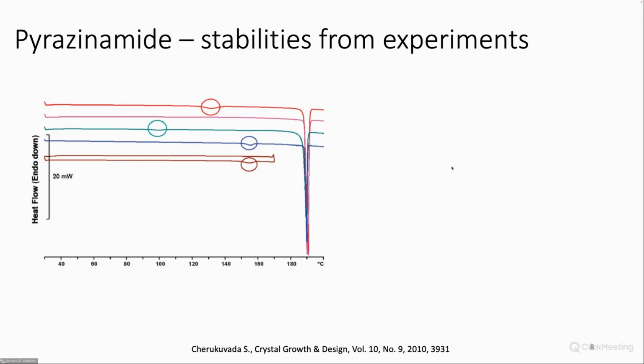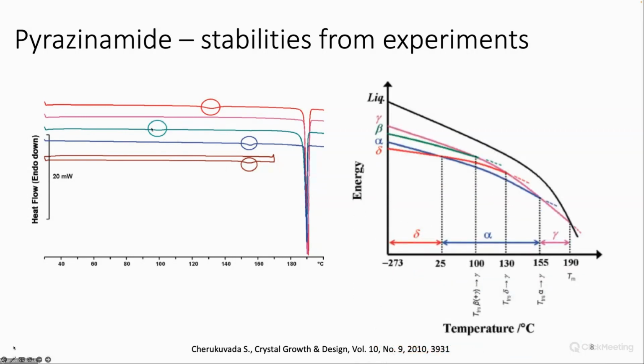But if we look at the thermal events that happen when we put the pyrazinamide forms, of which there are 4 different known polymorphic forms, into differential scanning calorimetry equipment, what we observe is a number of phase transitions, and we observe that all the polymorphic forms actually transform or melt at exactly the same temperature. And that's because they all transform to the same form during the heating process. So if we take note of these different solid state transformations that we can observe in the DSC here, then we can construct a temperature energy diagram.